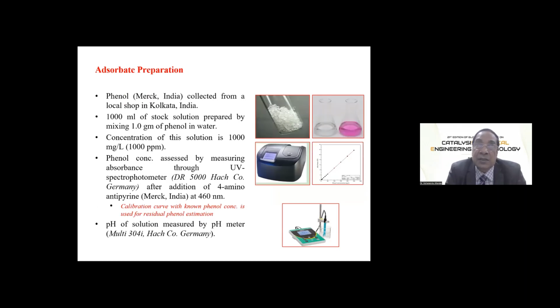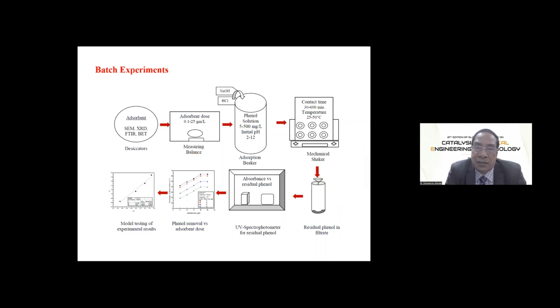Now, in case of phenol preparation, we have taken 1 gram of phenol in 1000 milliliter of stock solution, so that 1000 ppm or 1000 milligram per liter is the stock solution concentration, and that can be diluted as and when required to change our concentration of initial phenol. Then after adsorption, we will be getting some residual phenol, and if you would like to know what that quantum is, we will be measuring its absorbance through a UV spectrophotometer. Initially, we will be taking some known concentrations, and finally, after making the calibration chart with respect to absorbance, we will be evaluating the residual phenol after adsorption. And pH is measured through a pH meter, and pH variation is done with the addition of sodium hydroxide and hydrochloric acid.